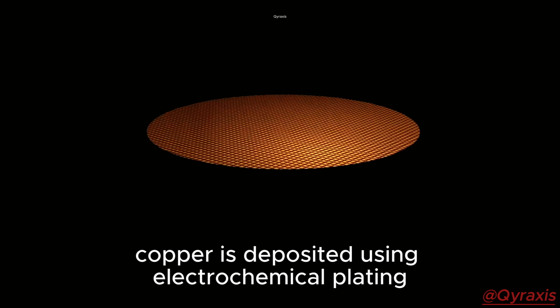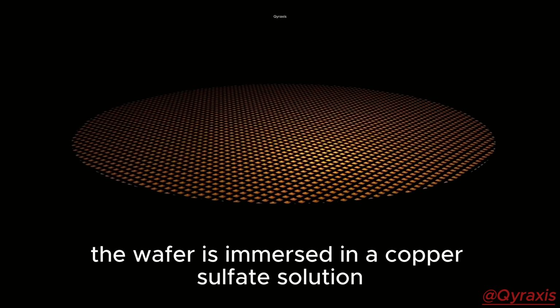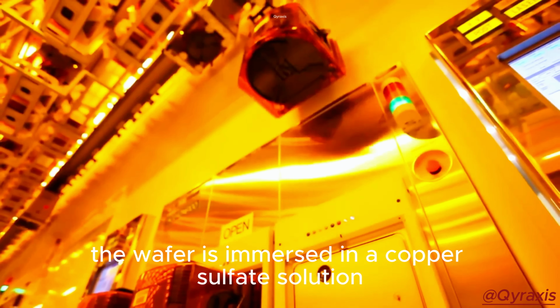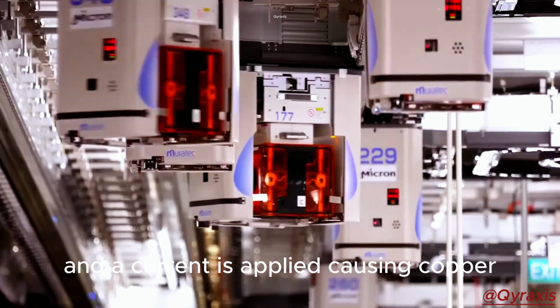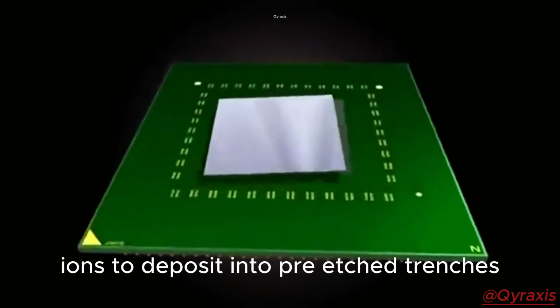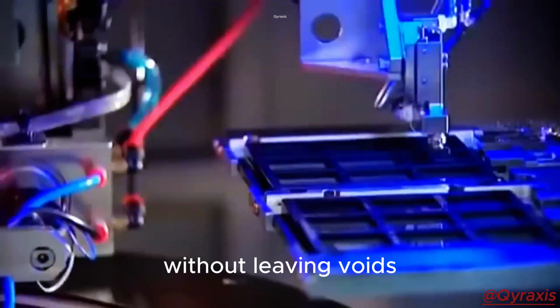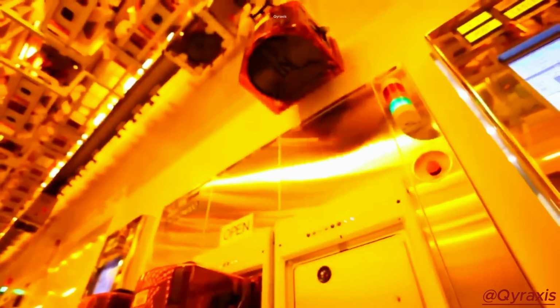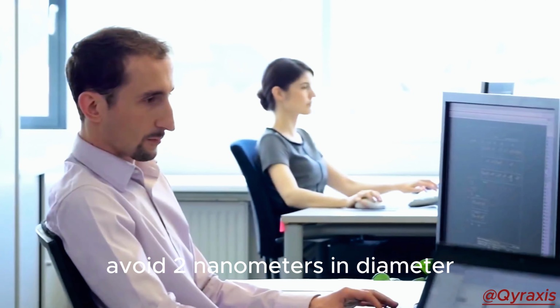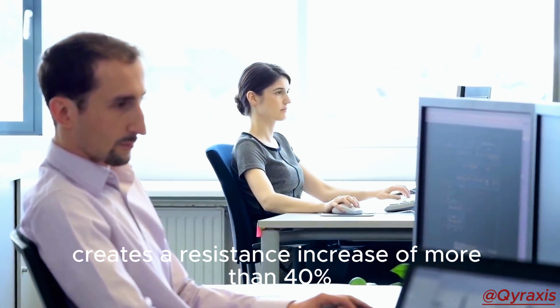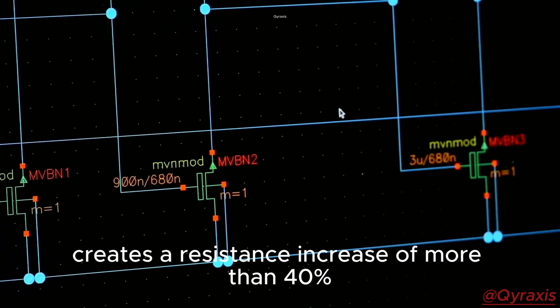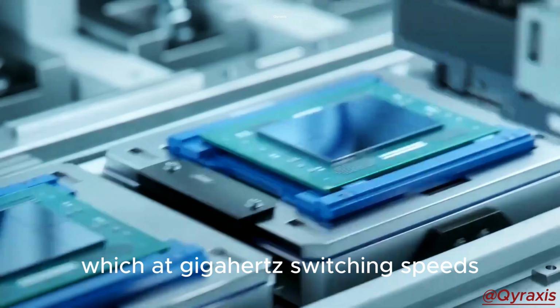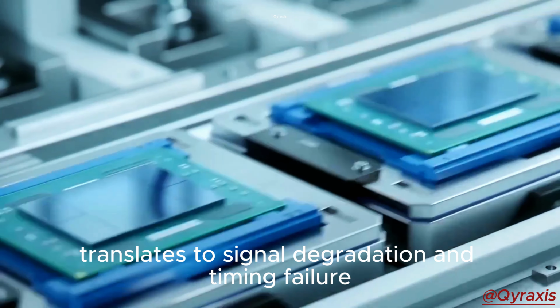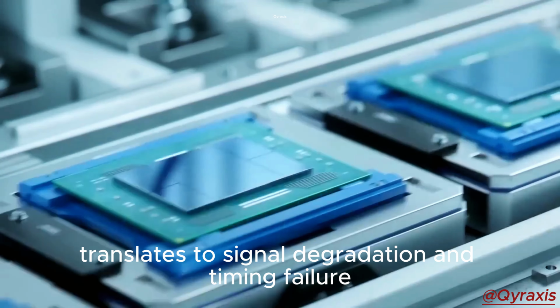Copper is deposited using electrochemical plating. The wafer is immersed in a copper sulfate solution, and a current is applied, causing copper ions to deposit into pre-etched trenches. The process must fill trenches as narrow as 5 nanometers without leaving voids. A void 2 nanometers in diameter inside a copper line creates a resistance increase of more than 40%, which at gigahertz switching speeds translates to signal degradation and timing failure.